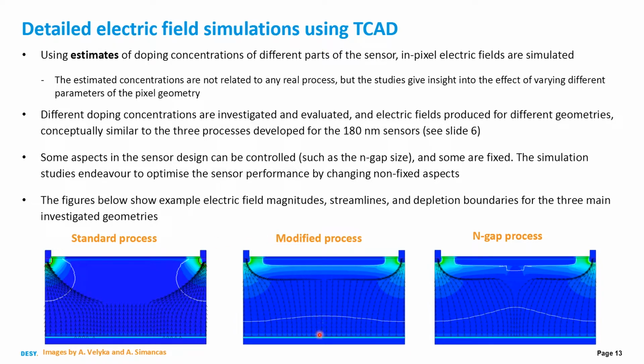For the modified process, you can see that the collection electrodes are at the corners here, sorry, I should have mentioned, rather than in the center. So here in the middle, between 2 pixels, the field lines for the modified process are rather straight, but as I mentioned earlier, if we introduce the n-gap, we can push the field more towards the collection electrode. And this can be seen here in the streamlines. They actually go more towards the collection electrodes, which is nice.